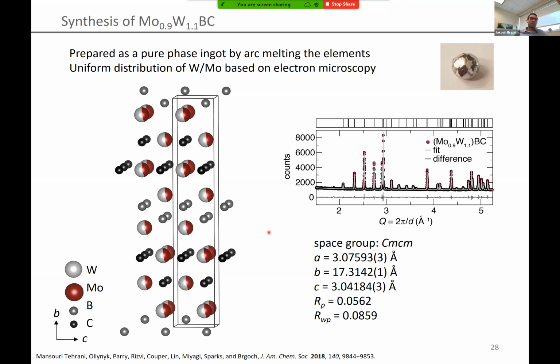Looking at the crystal structure, you can see that it's orthorhombic, actually pseudo-tetragonal. But one thing that's really an oddity about this crystal structure is that A is about 3 angstroms, C is 3 angstroms, but B is this really long length, 17 angstroms. So it's a super anisotropic crystal structure.